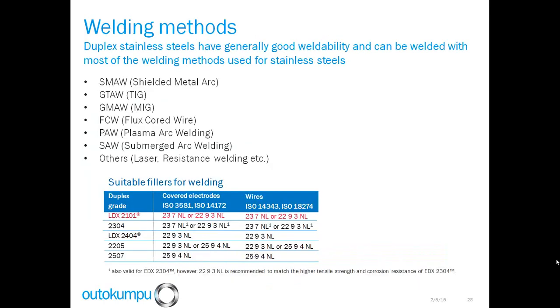When we look at welding, all the typical stainless steel welding methods can be used. The one thing you want to be sure with welding duplex is you want to use the appropriate filler metal. In all cases, you want to try to use a filler metal. Again, the object here is to maintain the austenite-ferrite balance, and that's only done when you use the correct filler metal when welding duplex stainless steel.